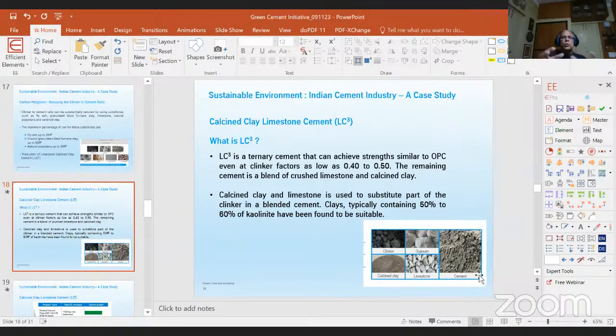Now, those who know a little bit of the cement chemistry, obviously the question will come, how just a limestone without being calcined can be used in the final cement? The answer to that is because of the calcined clay. Now, when you partially calcine the clay, it will make it highly reactive. Now, this highly reactive calcined clay along with cement and the classical clinker will give you all the attributes of a normal cement. Now, calcined clay and limestone is used to substitute the part of clinker in blended cement.